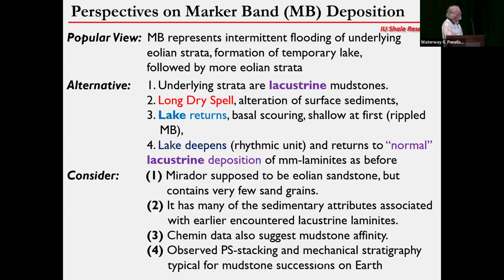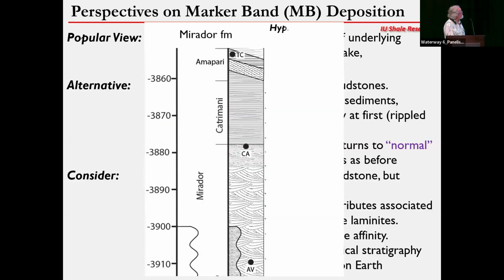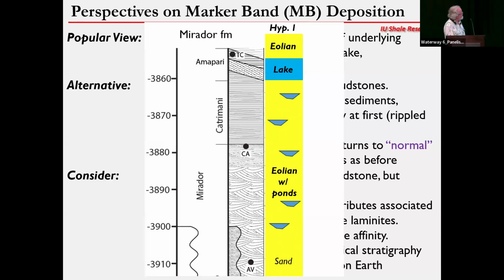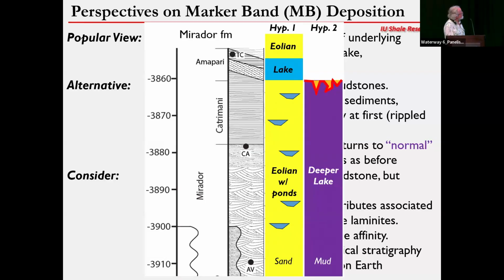And the reason why we think so is that it's really difficult in any MAHLI picture of Mirador to see any sand grains. We see sedimentary attributes that are seen in earlier encountered lacustrine laminites. And also the ChemMin data suggests some mudstone affinity. And we also see parasequence stacking and stuff like this that's typical of mudstone successions on Earth. So this is a community model, and this is our alternative model where we look at primarily lacustrine setting, but maybe with some Aeolian intervals interspersed with it instead of the other way around.